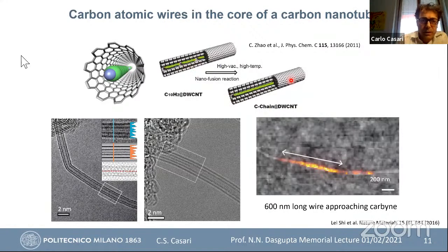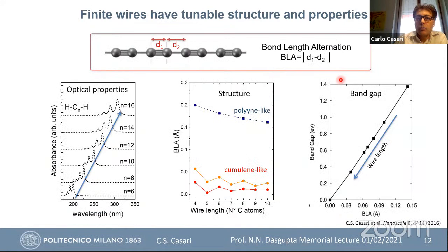And with a similar process, Lei Shi in 2016 was able to show, I would say, the longest wire inside a carbon nanotube that is really approaching carbyne, because they observed a wire 600 nanometers long, so composed of about 6,000 atoms, whose properties are no longer dependent on the size, and so this could really approach the property of the ideal case.